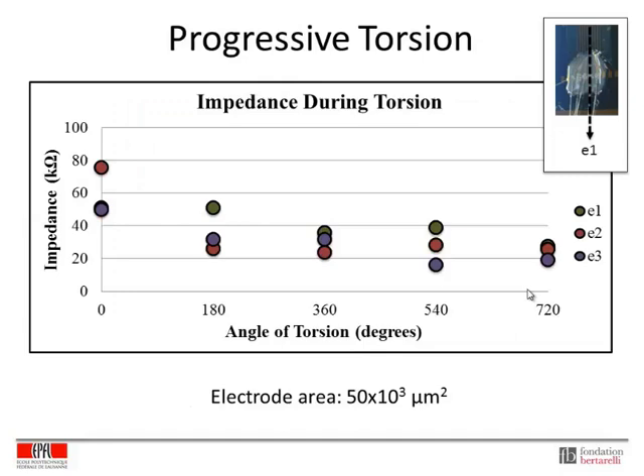These are some preliminary results of the behavior of the impedance as a function of the angle of torsion. We show 3 electrodes, E1 in green, E2 in red, and E3 in purple. The impedance of the electrodes are in the 20 to 75 kiloohm range, which is pretty similar to the impedance values found in the literature for electrodes of similar sizes.